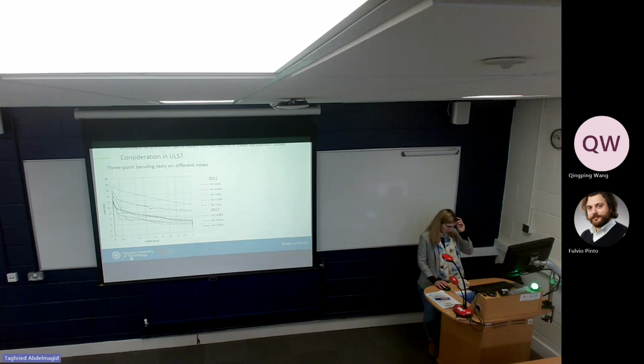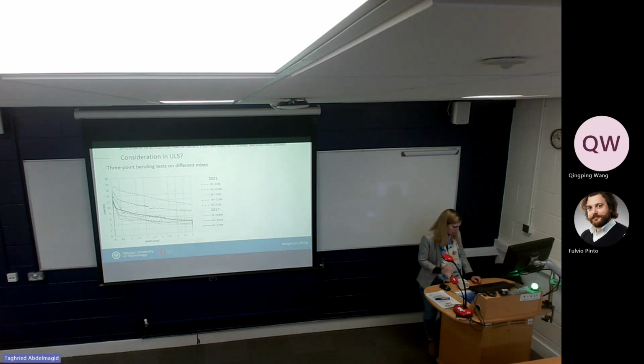And here I have more of these examples, and we also compared the results with friends from other universities in Poland. They have different fibers, also recycled, but from a different producer. Let's say the matrix was comparable, and we got almost the same values. This is a very good point, but it was self-compacting concrete, not normal concrete. So this is very important.